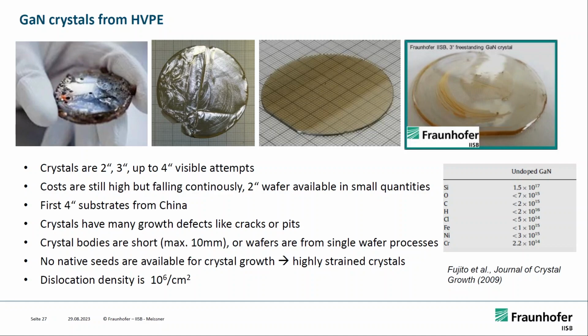The crystals are strongly strained because no real seeds exist, so you see uneven growth thickness - they grow like a hill. In your slices, the first wafer will be smaller than the second, and so on, which is often not acceptable. You can make wafers out of this, but you also have cracks, overgrown cracks, and all these issues. The dislocation density is 10 to the 6th, or 5 times 10 to the 5th, for the HVPE gallium nitride crystals.